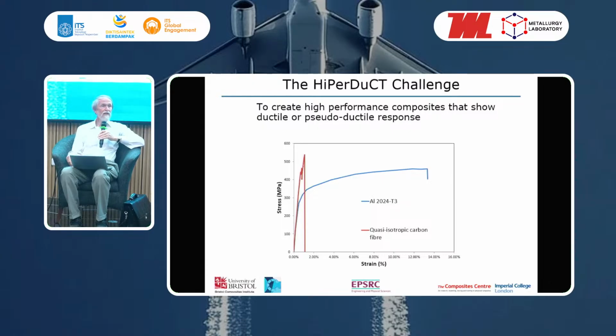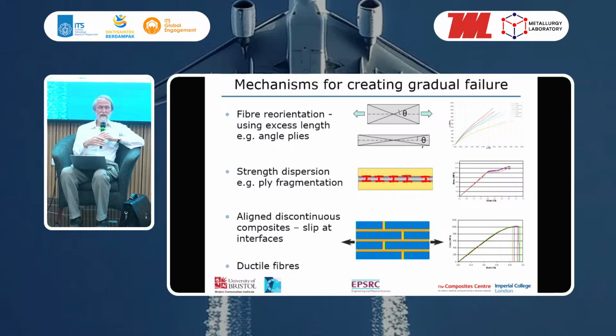We looked at various different ways of trying to achieve this ductility in composites, and the four main methods we looked at were, first of all, fiber reorientation. When you have angle plies, if the angle plies scissor, then you can get additional strain over and above the strain which is actually in the fibers, because the change in angle gives rise to a change in length, which produces additional strain. We had work on that, which was quite interesting. I'm not going to show you those results today, but you can see these nonlinear curves are a result of this change in angle. So this is a way of generating additional strain by reorienting the angles of the fibers.